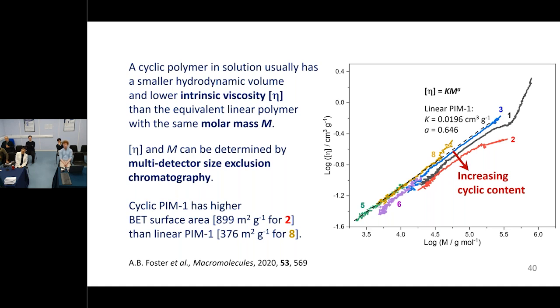And actually, if we have linear PIM1, the BET surface area is much lower than the default, because the polymerization model doesn't give you that. Other things are going on. Whereas cyclic-rich PIM1 has a very high surface area, because by tying the ends together, we've actually reduced the conformational flexibility even further.